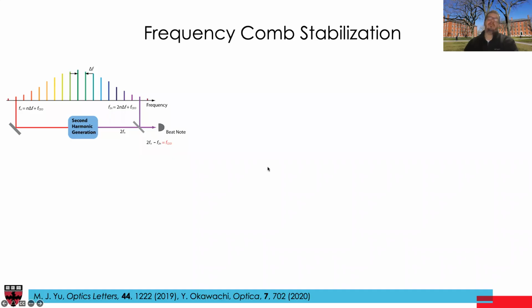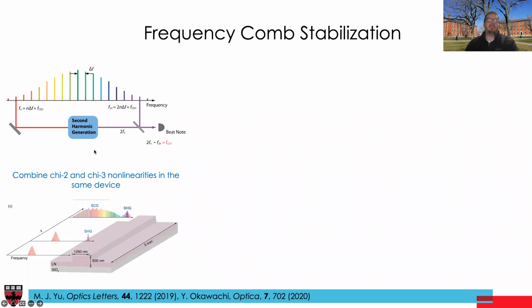What we have demonstrated too, but haven't combined with this platform, is frequency comb stabilization. I mentioned the goal is to make a broad comb so that you can detect the carrier envelope offset and make sure that the comb itself is stabilized, so that the envelope and actual optical signals don't slip. This is typically done by taking a broad comb spectrum and doubling one wavelength, comparing it to the frequency at the other end of the spectrum. And the beat note generates the carrier envelope offset frequency. This process of second harmonic generation is conventionally done with lithium niobate modulators. So our idea was, let's combine all of these things on the same lithium niobate chip.